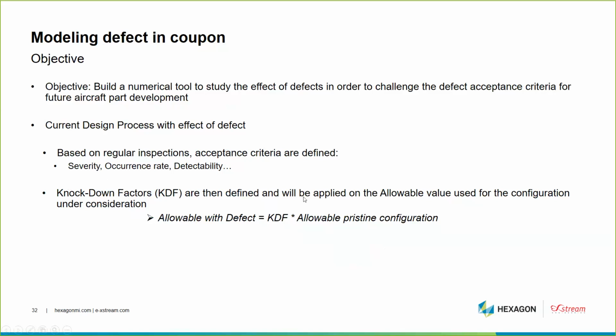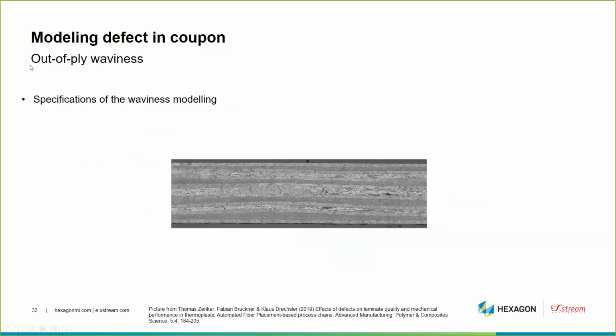So the first defect that we have to deal with is the out-of-ply waviness. And when we think about the waviness, we have to try to understand or to visualize what the out-of-ply waviness is in order to define properly the specification of the development. So if we check here, we see that when we have the waviness, the fiber orientation must follow the waviness of each ply.